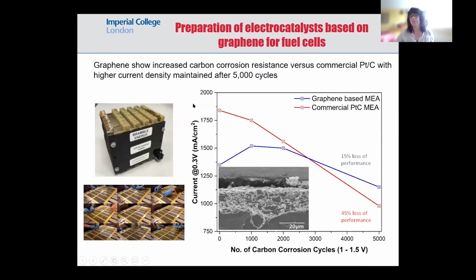And we have compared the performance of a graphene-based MEA here in blue compared to a commercial platinum on carbon. So we have studied the carbon corrosion over 5,000 cycles. The commercial platinum on carbon, even though it has an initially better performance, lost 45% of the performance after the 5,000 cycles, compared with the graphene-based MEA, which only lost 15% of the performance, which is promising, and it can be further optimized.